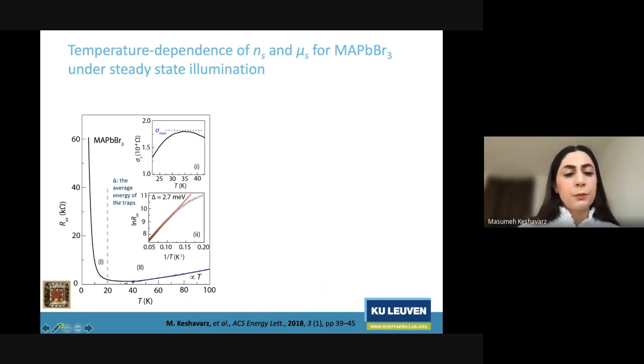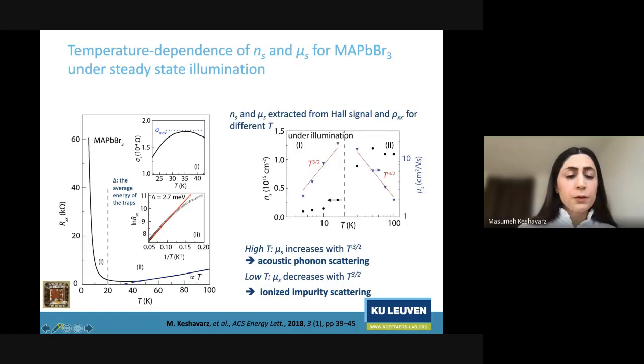So now let's look at the temperature dependence of the resistance, for example, for methylammonium lead bromide. We measured between 4.2 and 100 Kelvin because we wanted to always stay in the same structural phase. With temperature, the resistance scales linearly until it reaches a minimum, which shows a maximum conductivity. We can extract a maximum conductivity from this point, and then it starts increasing exponentially. So we can identify two distinct regimes, regime 1 and 2 here. In regime 1, the carrier transport is governed by the hopping of the carriers, and from the Arrhenius plot, we can extract the activation energy for that. You see it in the inset.